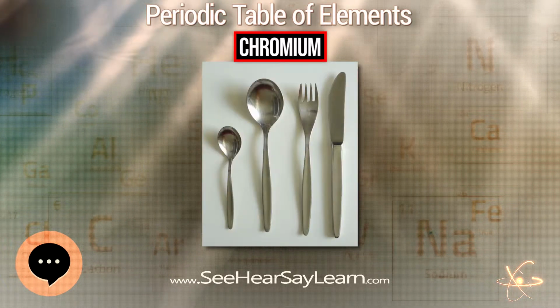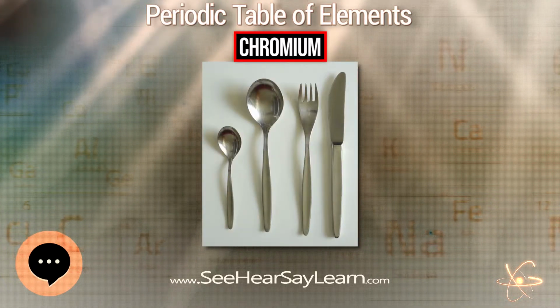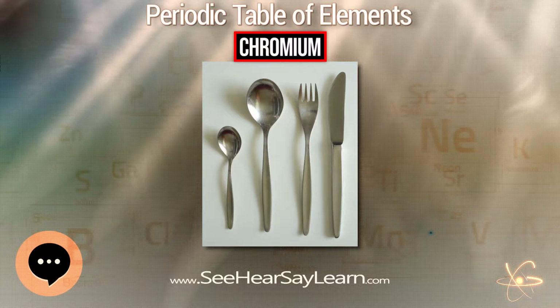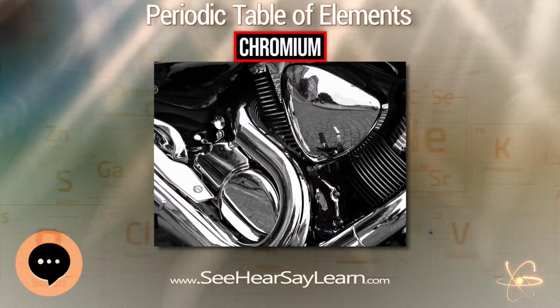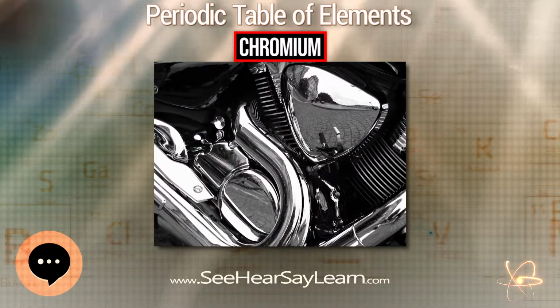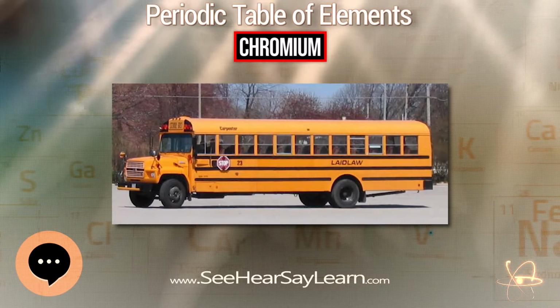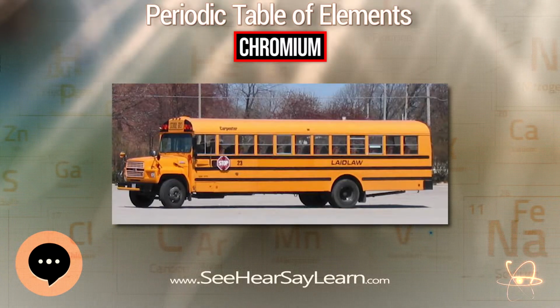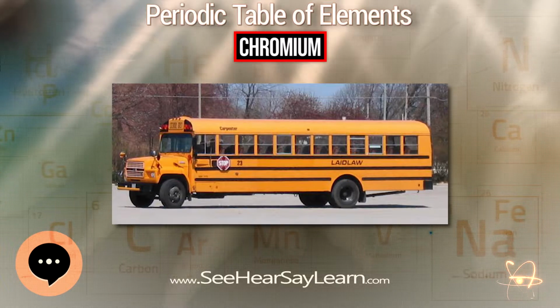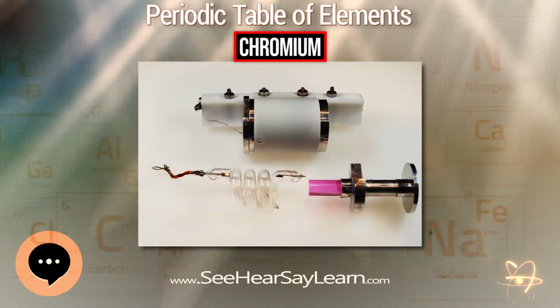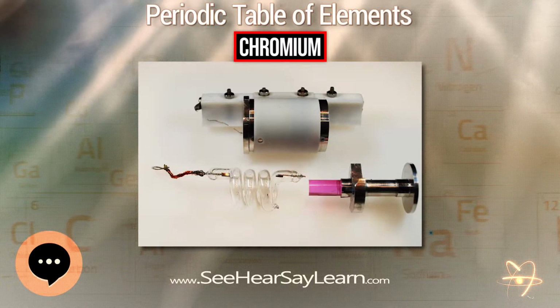layer of chromium oxide. Still, this oxide layer that was found on the weapons was not pure chromium metal or chrome plating as it is commonly produced today, but a mere 10 to 15 μm layer of chromium oxide molecules at up to 2% chromium was discovered, which turned out to be enough to protect the bronze from corroding.